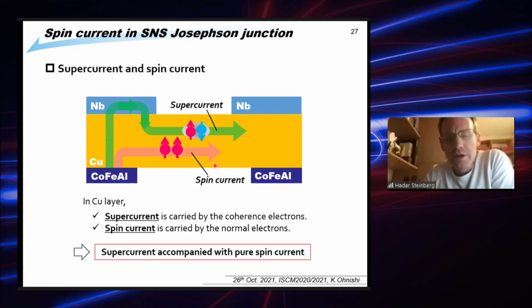My point is that it's common to look at such systems through the chemical potentials of the populations. You can look at the spin-up chemical potential and spin-down chemical potential, which is the way you look at spintronic systems. But now you add to this already complicated system a third component, which makes things much more interesting: the proximitized carriers. How much can you say about the rate at which these various populations equilibrate? Because it sounds to me that in this geometry one has to think very carefully about whether the spin up, spin down, and Cooper pairs are at all in equilibrium with each other. I'm wondering if you have any idea of probing this, maybe using a tunnel contact from the side or something. I don't think it's an easy thing to do.